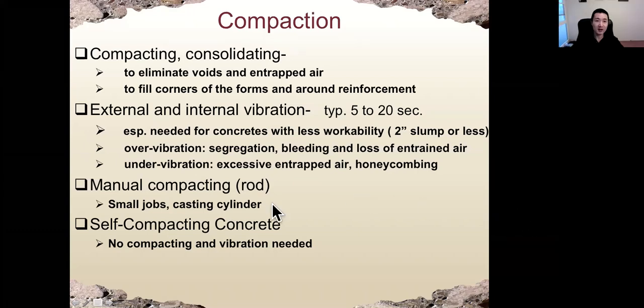The reason we compact concrete is to get rid of voids and entrapped air. Entrapped air is the bad air, in millimeter size, in the concrete not on purpose. We also have entrained air, which is added by an air entraining agent, one type of chemical admixture. Entrained air is good air, but entrapped air is bad air. We also compact to fill every corner of the formwork and around the reinforcement. That's the reason we need to compact concrete.